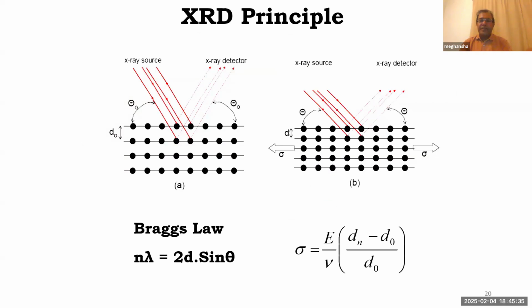We know that material structure is made of various planes. So the slide is indicating various planes, and we can indicate the distance between two planes as D0. D0 is the distance or interplanar distance between two crystallographic planes. So this D0 or distance between crystallographic planes is very much important. If I pull the component like this, then this D will become low. So this direction of elongation or stress, or tensile residual stress, will reduce the D interplanar distance. And if we compress the component, it will increase the D. So by measurement of D, we can assess the amount of residual stress. So this X-ray diffraction technique uses X-ray, and this X-ray measures the D whether it is increasing or decreasing. So by using this measurement of D and Bragg's law, we can calculate the amount of residual stress inside the component by this mathematical expression.